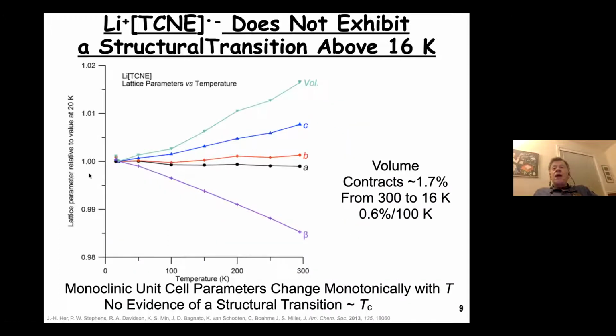So we ruled out a structural change. We looked at the unit cell parameters for A, B, C, beta, and the volume, and they monotonically increased from 16 Kelvin up to 300 Kelvin, and there's no glitch in the data suggestive of a structural transition. So this is totally a magnetic transition for this material.